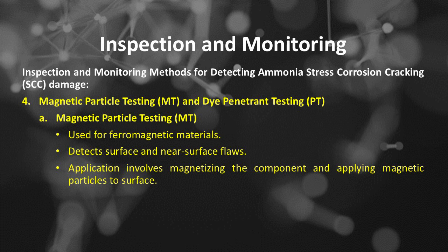Number 4 of inspection and monitoring methods for detecting ammonia stress corrosion cracking damage is magnetic particle testing, MT, and dye penetrant testing, PT. Number A, magnetic particle testing, or MT. MT is used for ferromagnetic materials, and to detect surface and near-surface flaws. Application of MT involves magnetizing the component and applying magnetic particles to the surface.